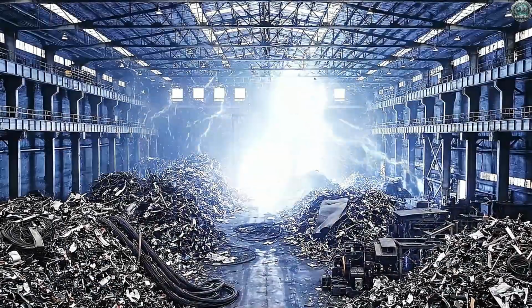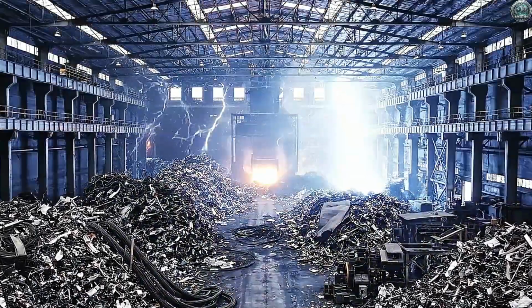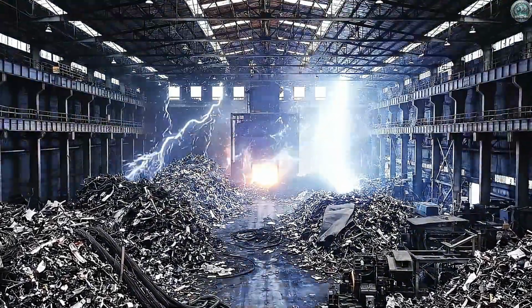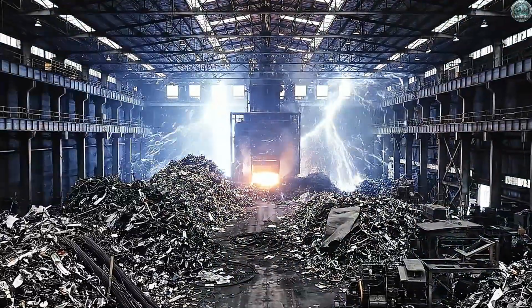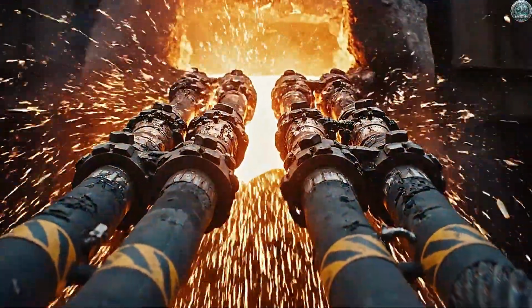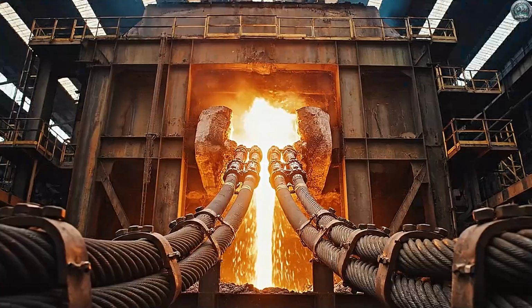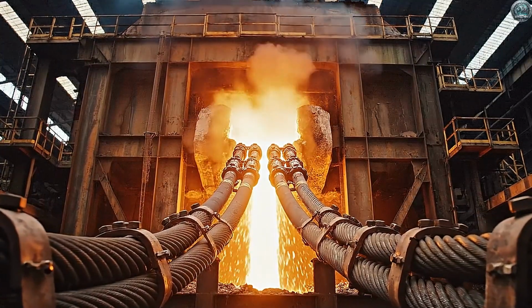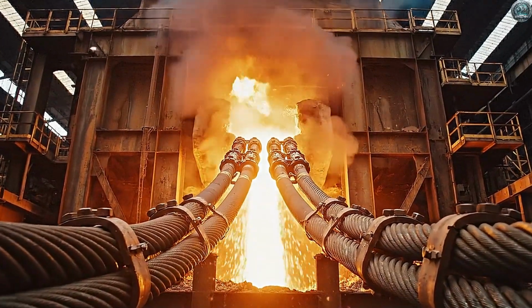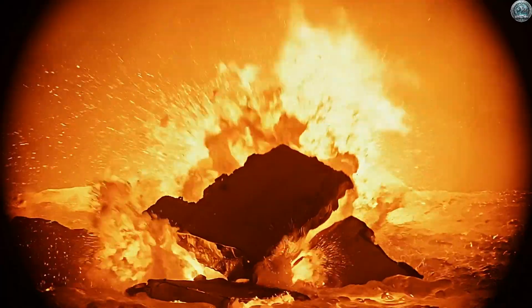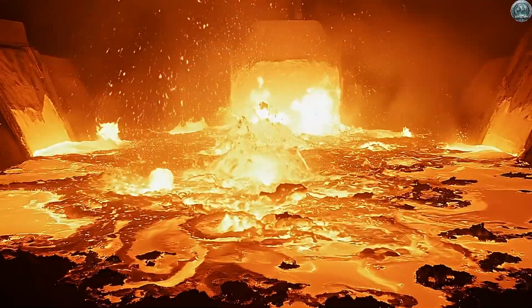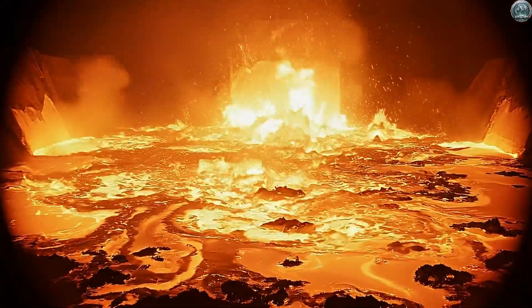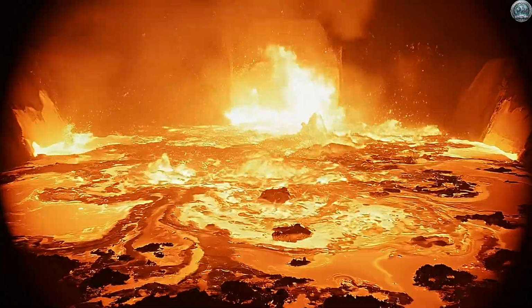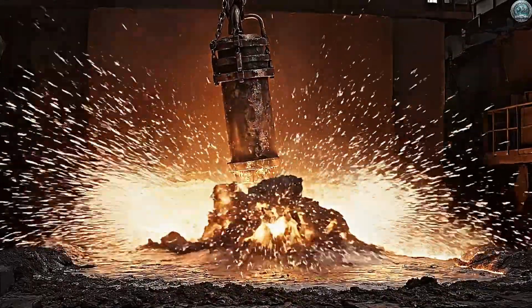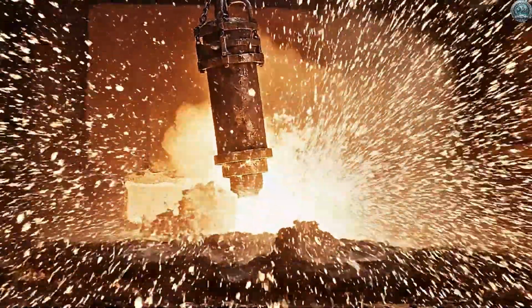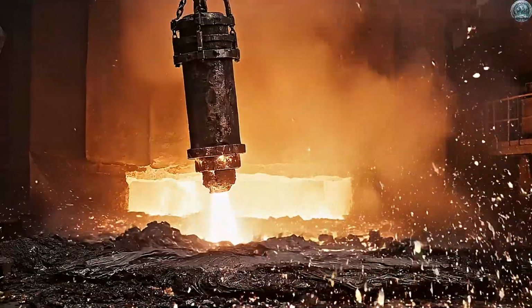100 million watts of raw electricity arc through the scrap, creating a violent thunderstorm indoors. Temperatures rapidly climb to 3,000 degrees Celsius, turning solid steel into flowing liquid fire instantly. Inside the furnace, the solid scrap collapses, surrendering to the heat and becoming a molten bath. Supersonic oxygen is injected to burn off impurities, creating a fierce reaction and a protective slag layer.